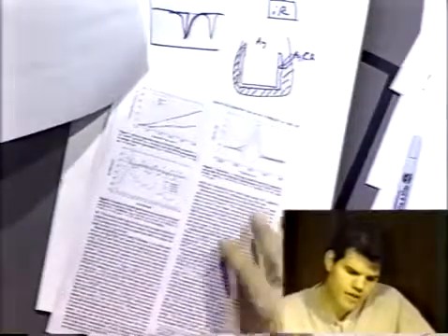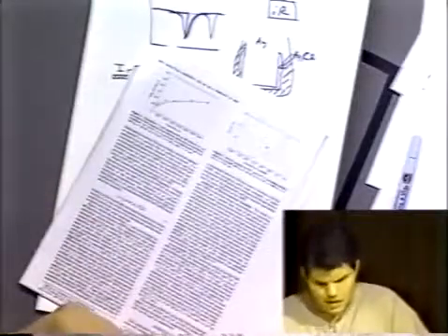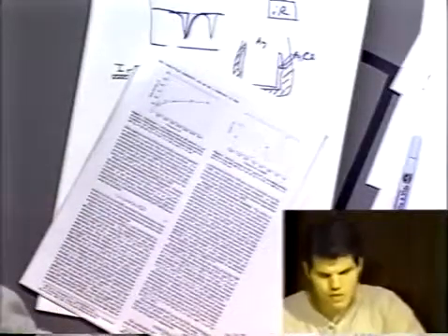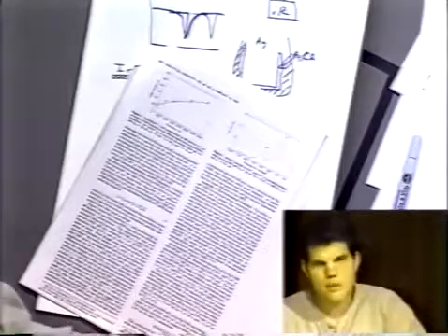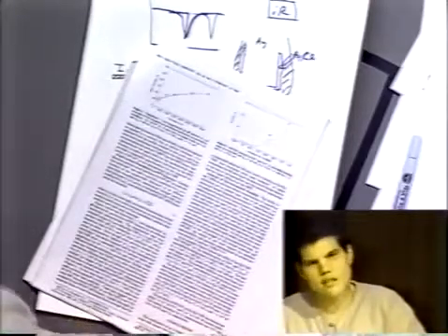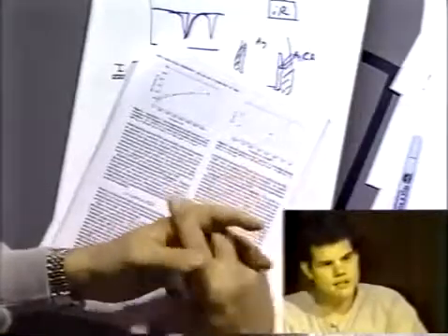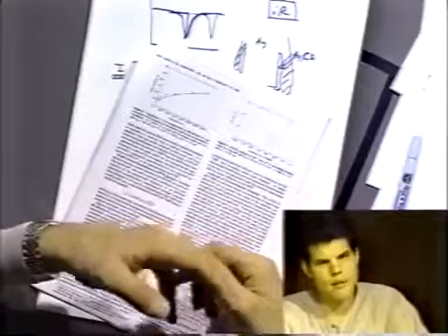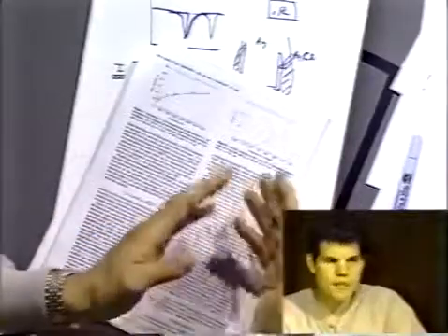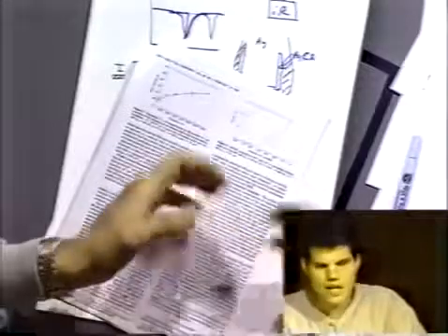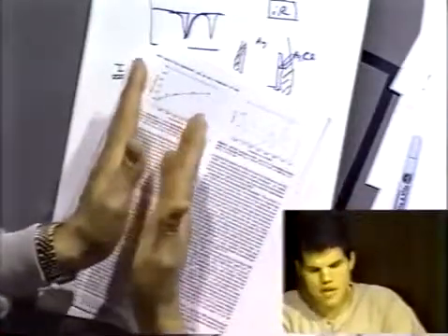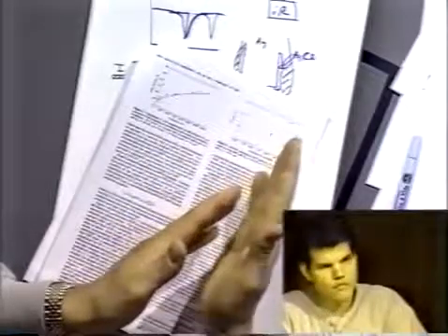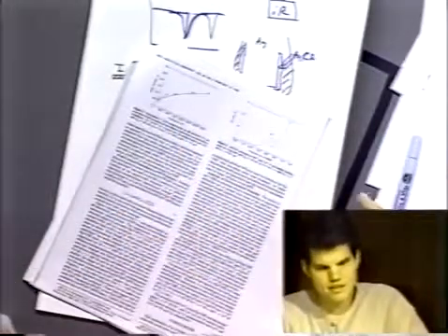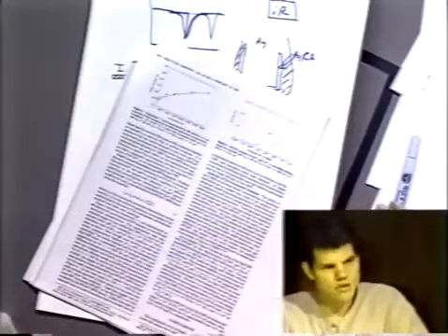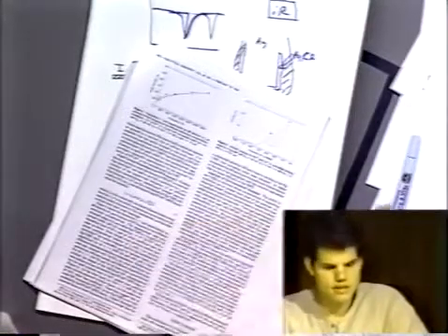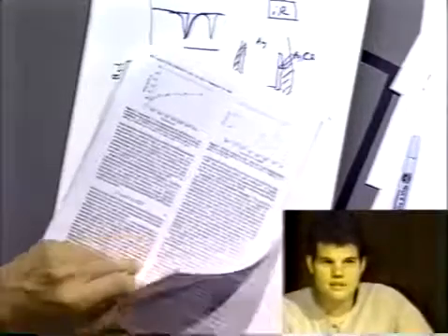And part of the reason for that is they've exploited the fact that oxygen tends to be somewhat sluggish electrochemically compared to some metal ions. So the reduction and oxidation rate constants for metal ions, especially out of a mercury amalgam, are usually very rapid, particularly for copper, cadmium and lead. And oxygen is slow. So what they're doing is they're making the experiment time frame fast enough so that the reduction of oxygen is kinetically slow, and so the current for that becomes very small, and you just don't see it. It's not part of the background.